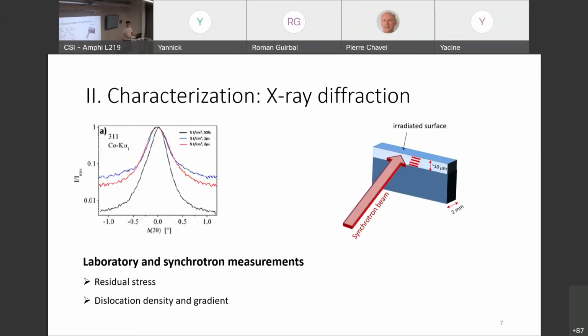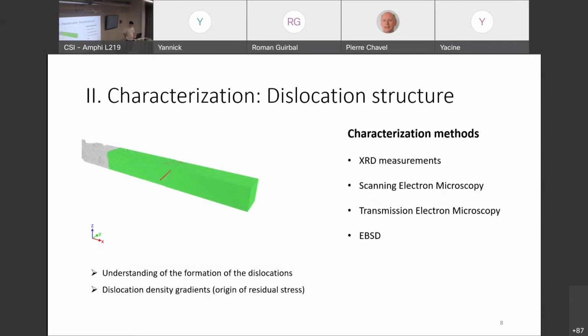First, we can do X-ray diffraction in the laboratory to understand the average behavior in the material, and then we'll do at the synchrotron some measurements to understand the link between the gradient of the pressure in the material and the gradient of the dislocations in the material, which will give us the understanding of the creation of those dislocations. And by understanding the creation of the dislocations, we'll know which is the origin of the residual stress. To do so, we'll use, as I said before, XRD measurements, but also SEM, TEM, and EBSD.